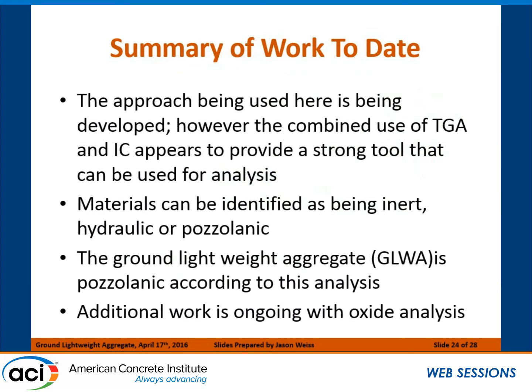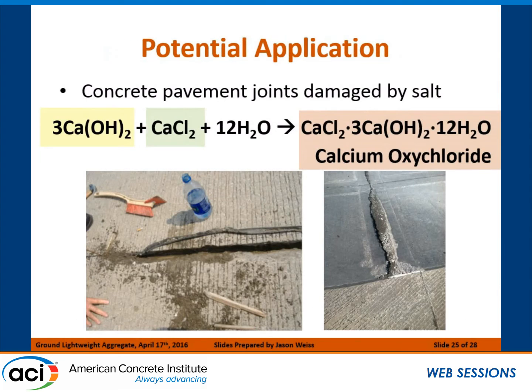So if we kind of summarize where we've been up to this point, the approach that we're developing here is really looking at TGA plus ion chromatography to provide a real strong tool for this analysis. This enables us to really identify materials as inert, hydraulic, or pozzolanic very quickly. The ground lightweight aggregate is incredibly pozzolanic when we start to look at this, and this really leads us into a really great potential application for these pozzolanic types of materials.